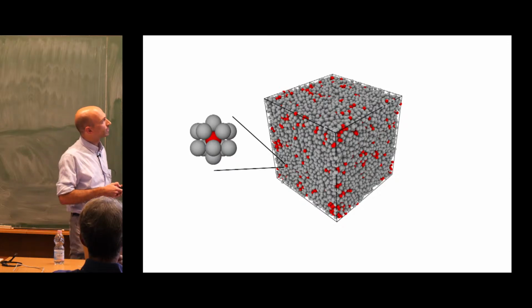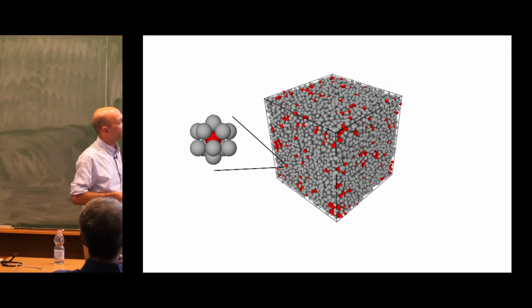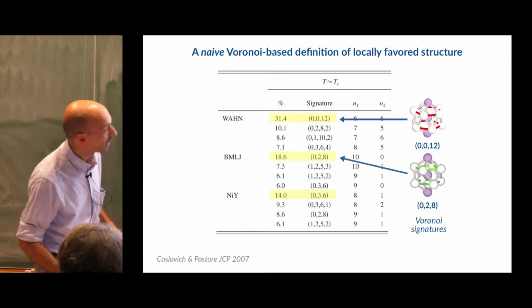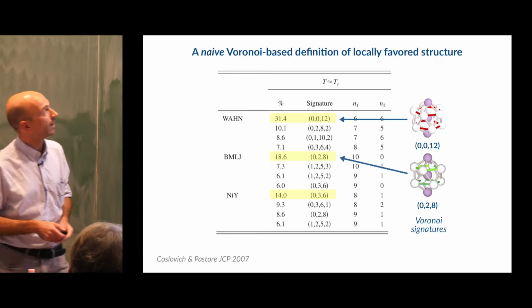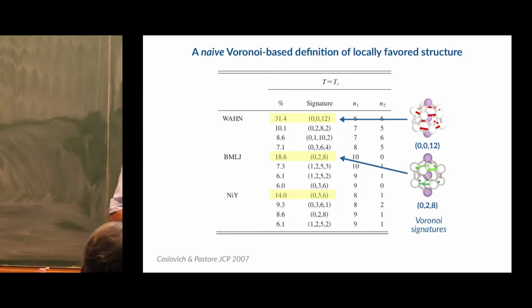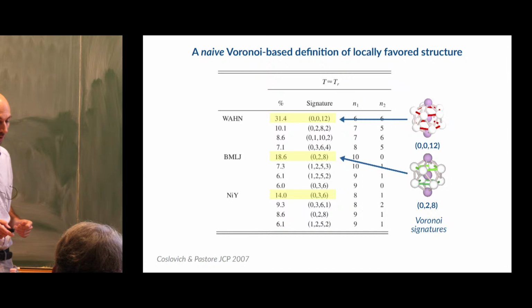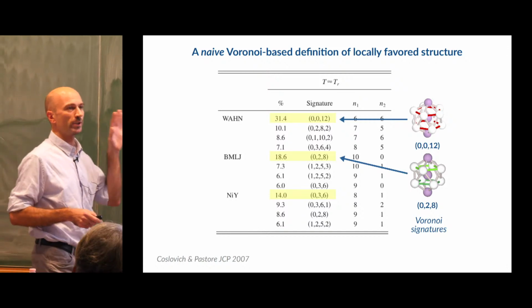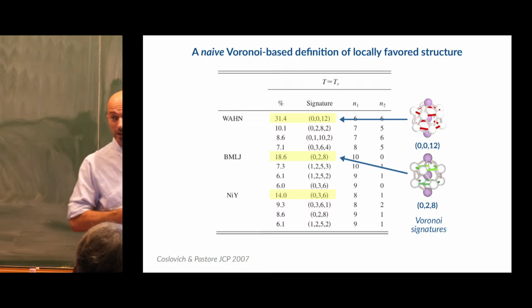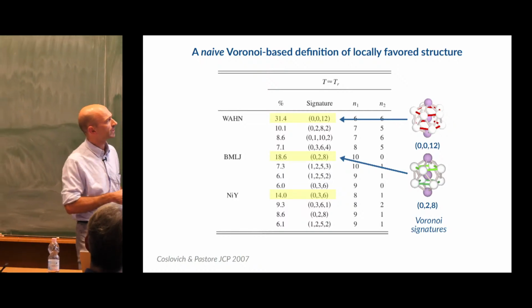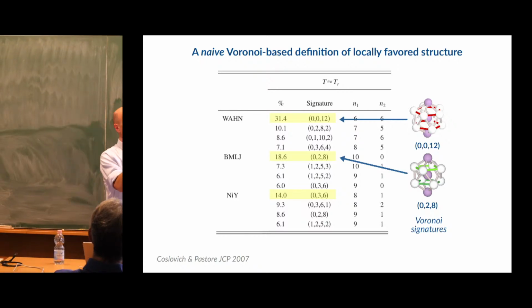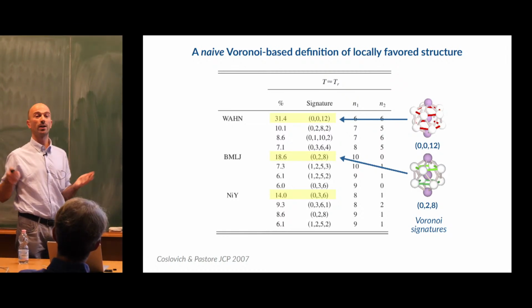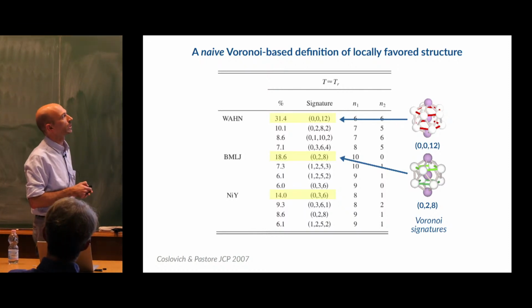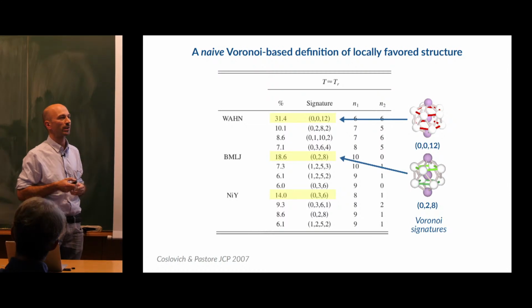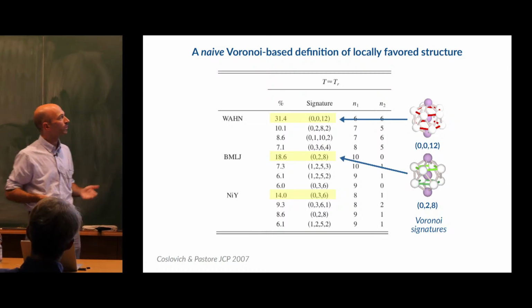All right. So in order to go through a definition of locally favored structure that is well founded, I would like to make first a bit of a history of how we got to these ideas. And I will start with a very naive, and I will call it Voronoi-based, definition of locally favored structure. This is what we used long ago for Lennard-Jones mixtures. And the idea is the following. You start from a Voronoi tessellation, and you look at the signatures of the Voronoi cells around each particle. So this is just a sequence of numbers that characterizes the shape of your local arrangements of the neighbors around the particle. And then you go to low temperature and make statistics and check which signatures are the most frequent ones. And those are, for you, the locally favored structure, the ones that get accumulated by the supercooled liquid as you lower the temperature.